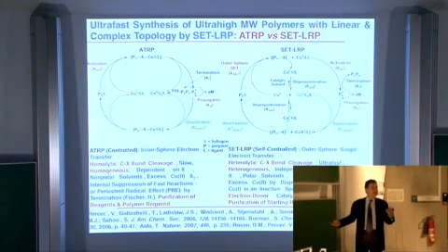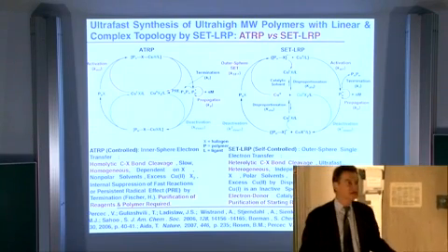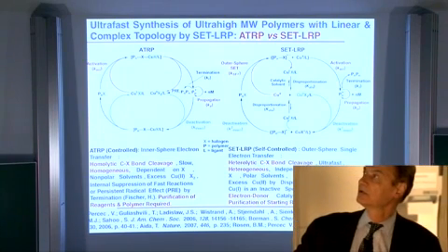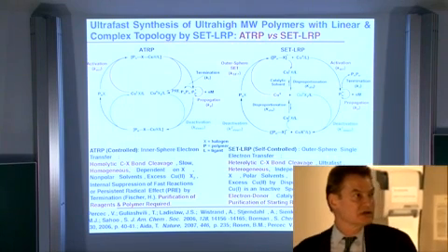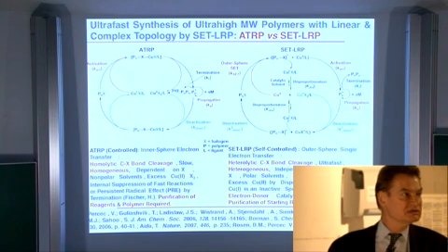The reaction becomes very slow. The polymer at the end of the reaction is colored, or the organic reagents are very colored. You need to purify everything by column chromatography because copper-1 and copper-2 are colored reagents. And a stoichiometric amount of copper-1 must be used in this reaction.